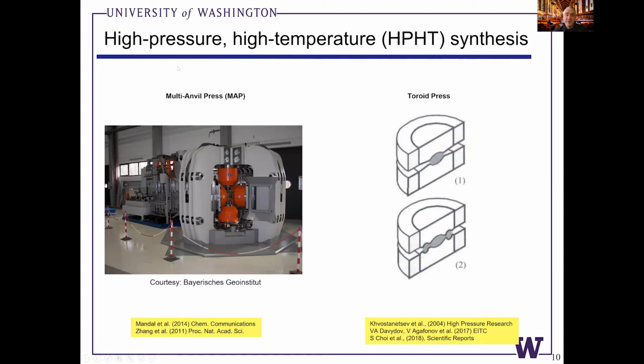But in the multi-anvil press or toroid press, you can grow large amounts, milligrams of material, get to very high pressures, 15 GPa or so, very high temperatures, over 1,000 degrees Celsius routinely, very easily. But a challenge is controlling the kinetics of this process. These things are slow to heat up, slow to cool down. And also it's difficult to see inside of the chamber when you're doing synthesis. It's hard to know what you're growing in real time.